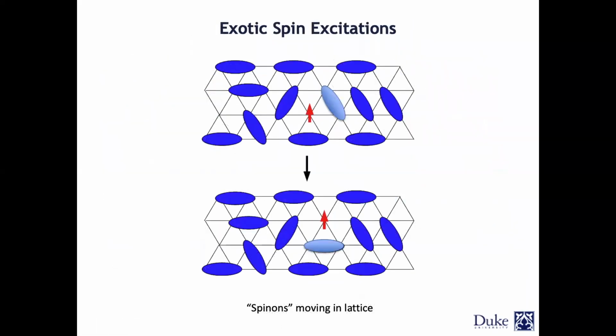Now, I am here also going to talk about these spinons, but again, this is going to be a very quick scenario of what these spinons are. So practically, spinons are excitations or quasi-particles that can emerge when you have a quantum spin liquid candidate and you break one of these bonds. So if, for example, here you're going to see that there is a spin half, which is not in any bond, which is not entangled with anyone. So what can happen is that now this guy is a spinon. So it does have a dispersion. It can start to move around.